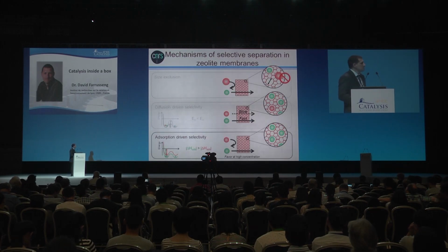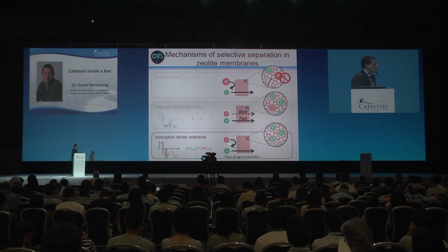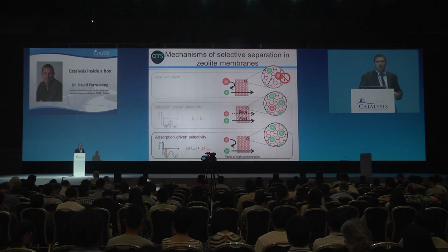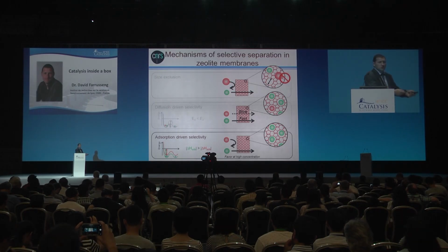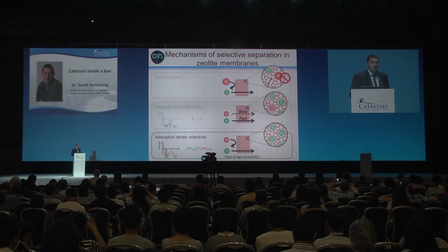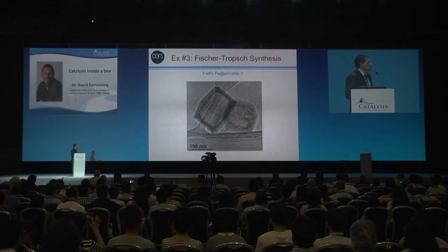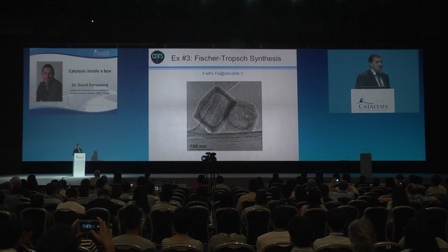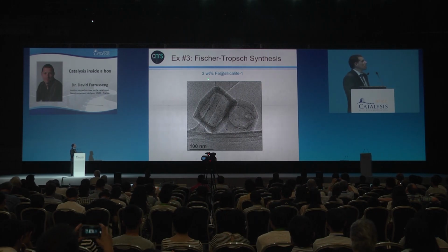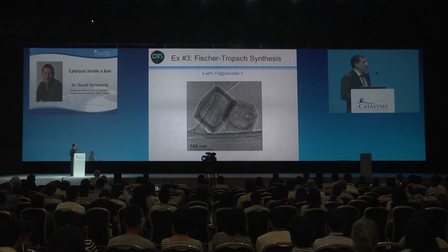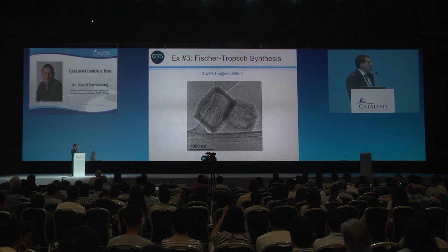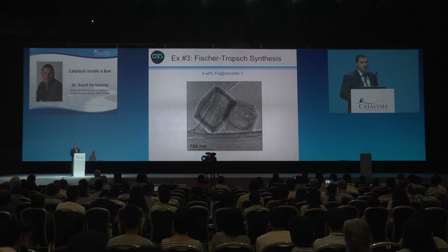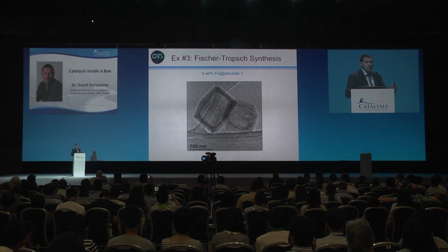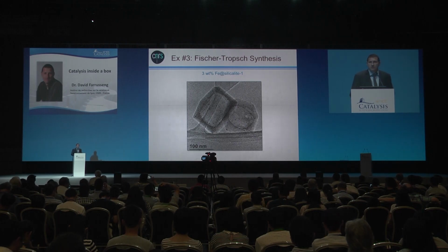The last case is where one reactant is much stronger than the other and pushes it away from the zeolite membrane. And for that, I've selected the case of Fischer-Tropsch catalysis. You can see here 3% of iron in silicalite 1. The black spots are the iron nanoparticles. In this case, you don't have a single particle again, but many small particles. And it's hard here to say where these nanoparticles are located.